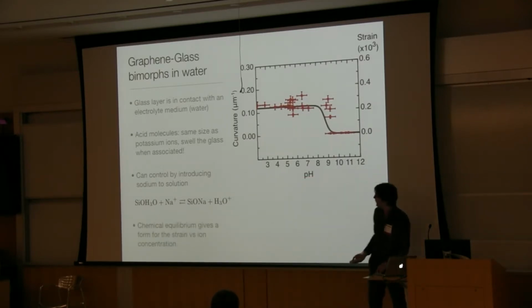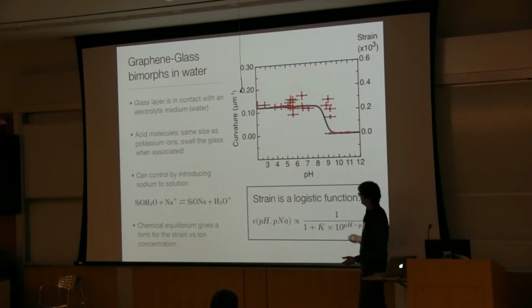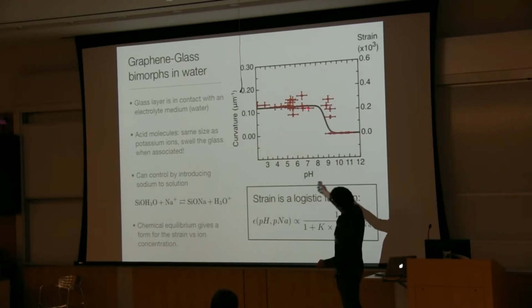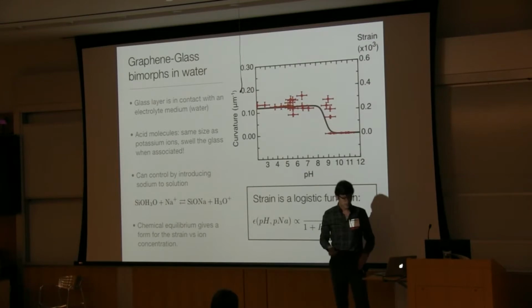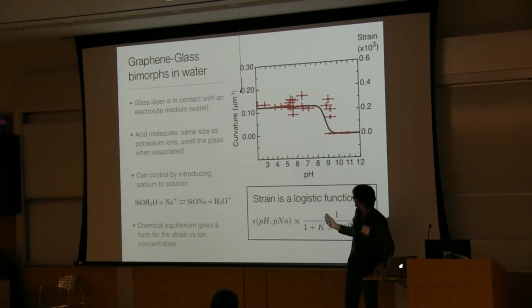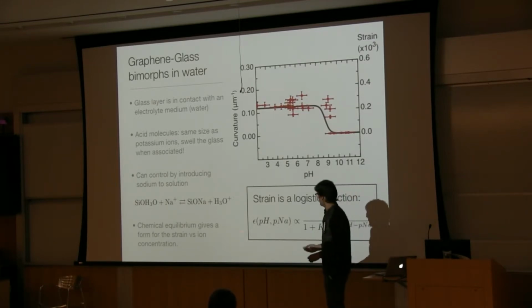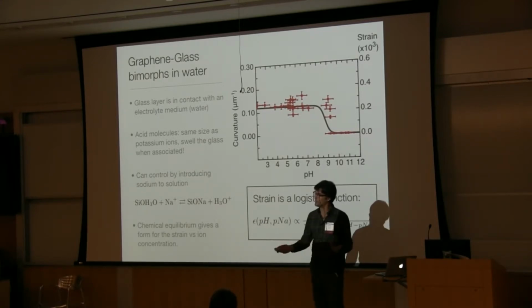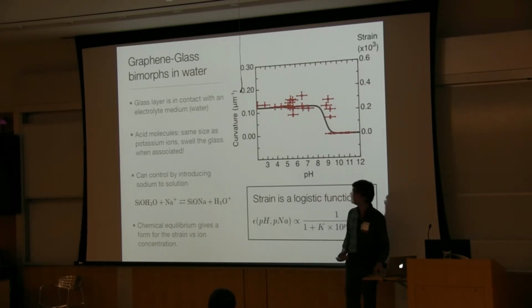You can work out, again, if this goes to chemical equilibrium and the strain is really due to the acid molecules, that gives you a functional form for the strain, and from there you can get a best fit to the line and come to the conclusion that you understand this mechanism reasonably well. What's neat is that this then tells you the curvature as a function of all the relevant environmental conditions, the pH, the pNa, and also the temperature combined with the previous graph.